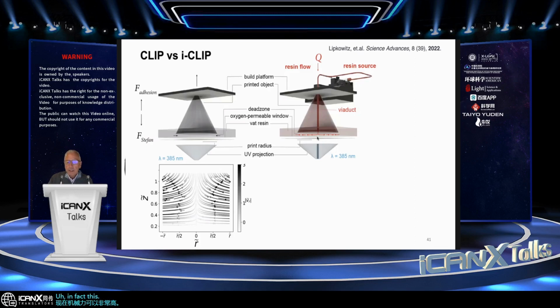In fact, instead of the object here kind of sticking to the window and you're trying to lift it up like two plates of glass with a drop of water between them, now we're injecting resin into that gap, and it's kind of like a rocket engine. You can actually push it off the surface if you're not careful. And so you have to control forces here even more carefully.